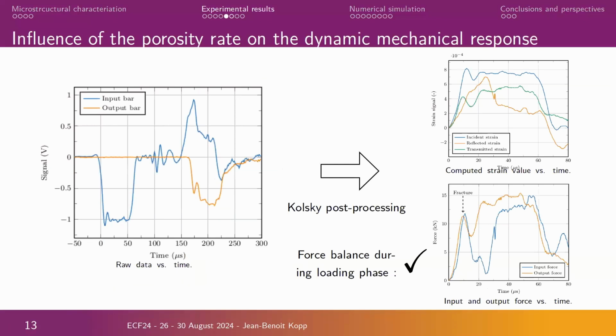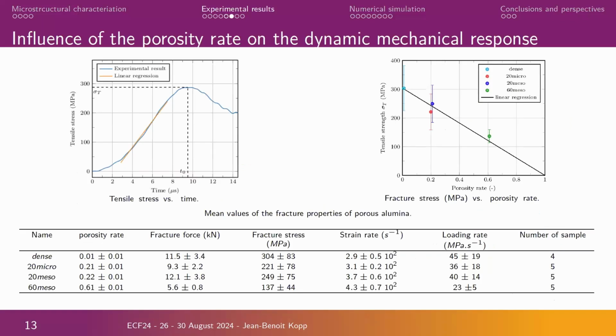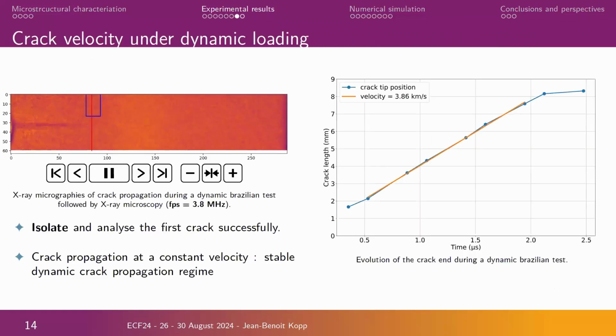So of course it is possible to estimate the stress applied just before failure, but we have to be sure that we have quite an equilibrium between the force in the different bars. So we just have checked that. And finally, we can evaluate first of all the fracture stress as a function of the porosity rate just over there, as it is expected. The bigger the porosity rate, the lower the tensile strength. As we can check just over there.